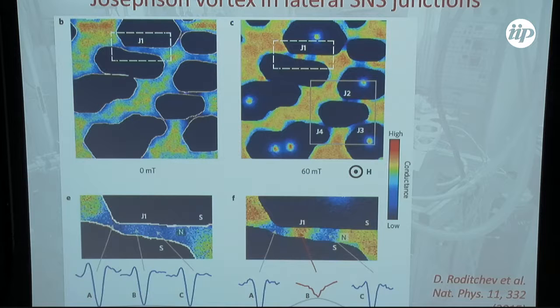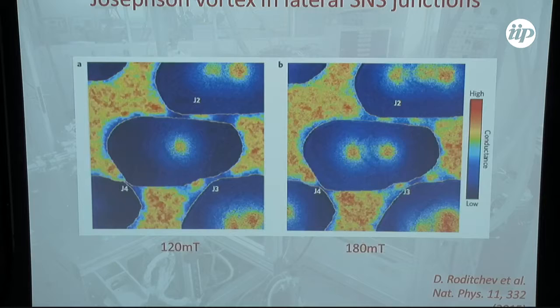I can convince you also, if you look at these junctions, there are three of them. If I apply a magnetic field of 120 millitesla, I will have one vortex here, in this position. If I apply a field of 180 millitesla, I recover a proximity link here, and I will have two cores there. The same situation appears here. And no vortex exists here, because the junction is too short and you cannot fit one Josephson vortex core inside. So the physics of the effect is very simple.